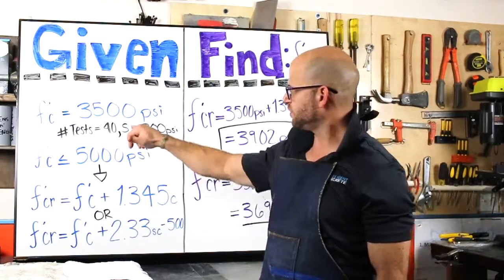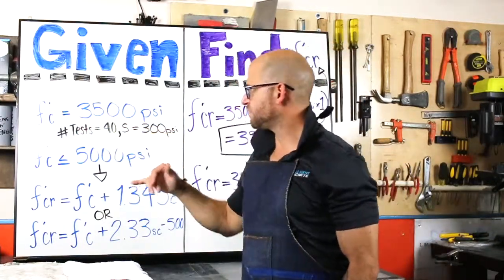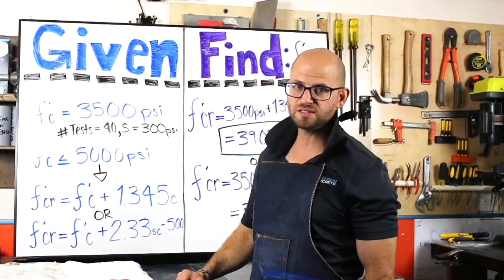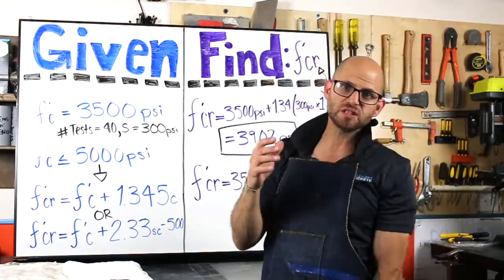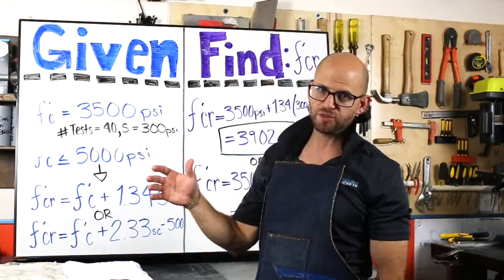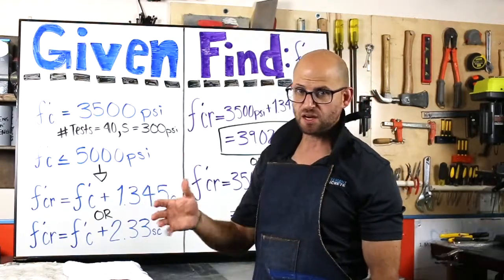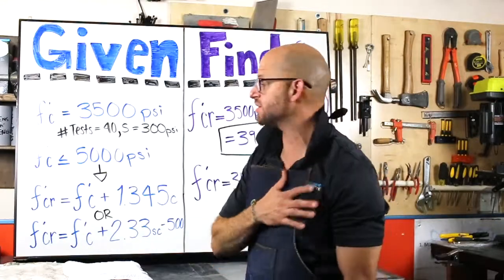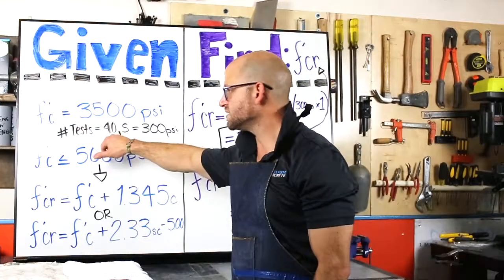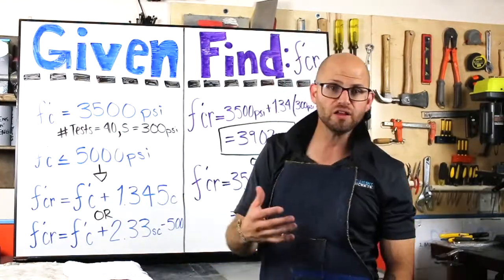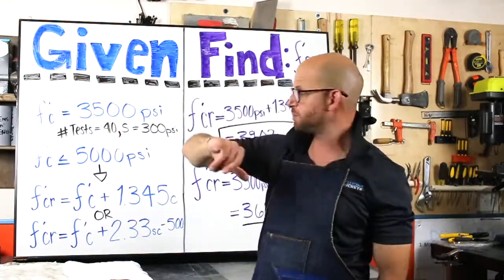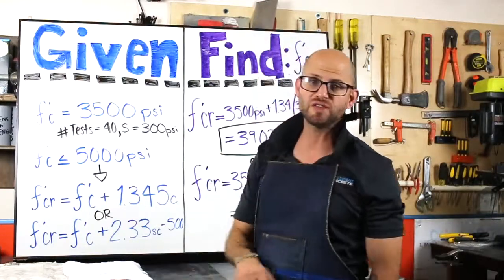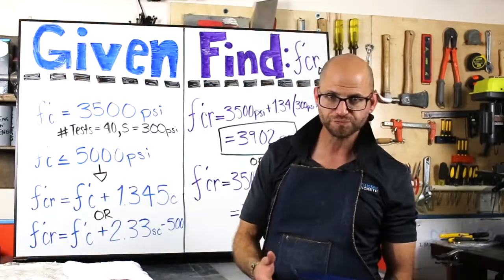So let's say for a certain concrete, we have 3,500 PSI 28-day design strength from the engineer. We've used the concrete over a 3-year time frame, and we've tested the concrete, assuming that I'm the ready mix provider, and we've got 40 different sets of tests on that concrete mix design, very specific mix design to give us the strength and the other properties, and the standard deviation of that mix is 300 PSI.